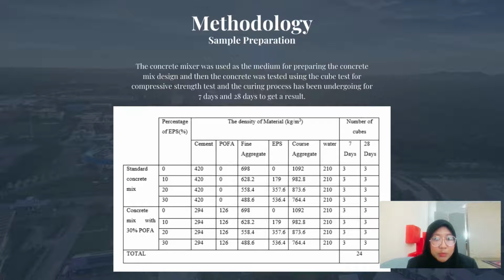For the methodology sample preparation, the concrete mix was used as the medium for preparing the concrete mix design, and the concrete was tested using the cube test for the compression test, and the curing process has been undergone for 7 days and 28 days to get the result. Okay, as we have shown, the total is 24. This is for the compression test.